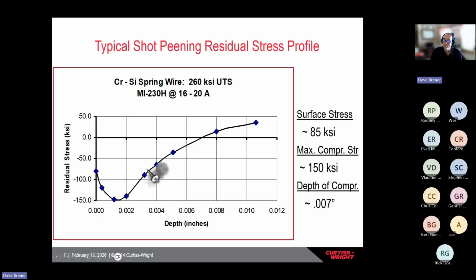Where the compressive stress crosses the neutral axis, which in this case is 7 thousandths deep, is also fairly easy to predict. The last variable is the surface compressive stress, which is almost always less than subsurface. Generally you want this more compressed, and this can be improved with a secondary dual peen. However, a single peen does work well for 90% of the applications.